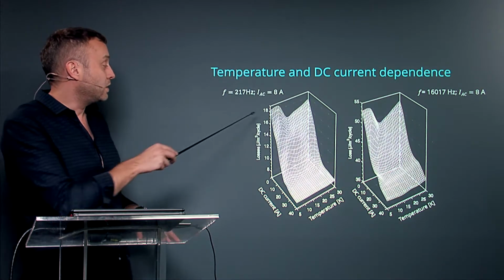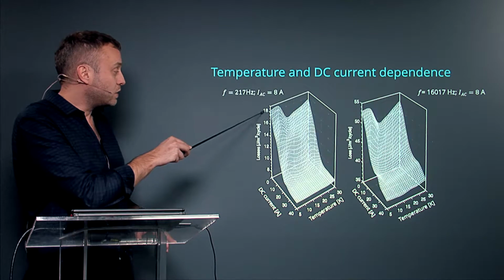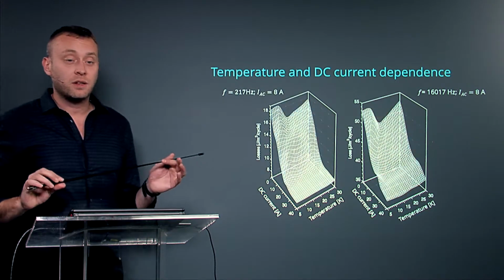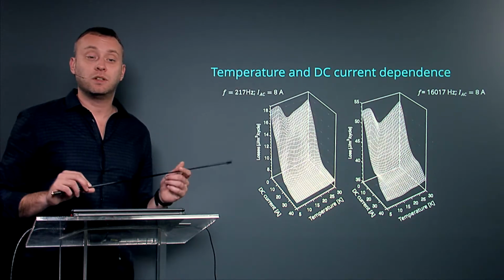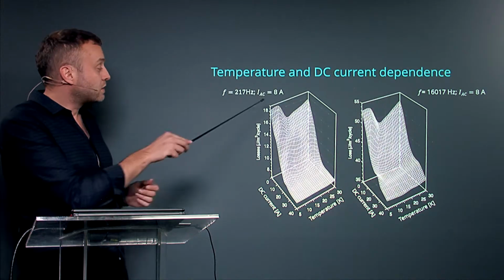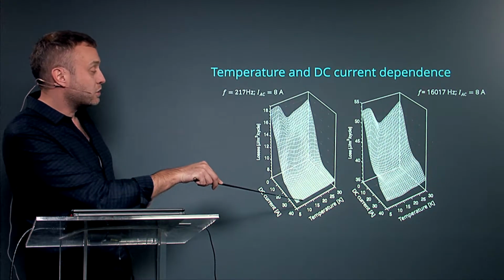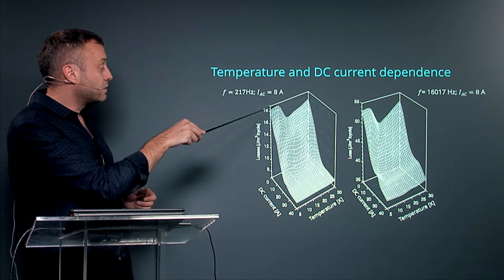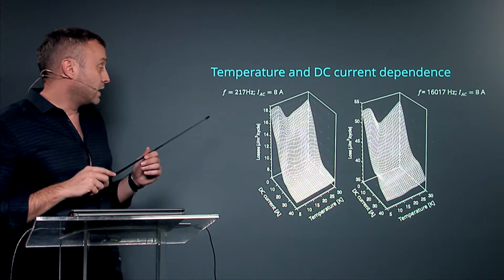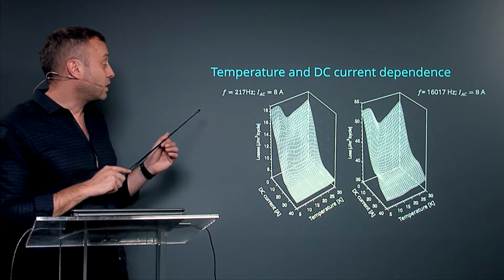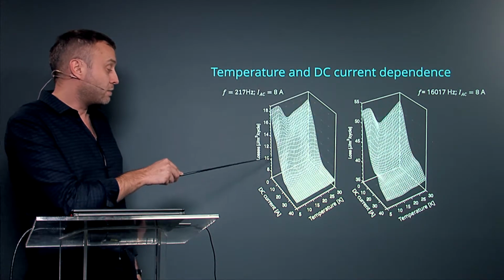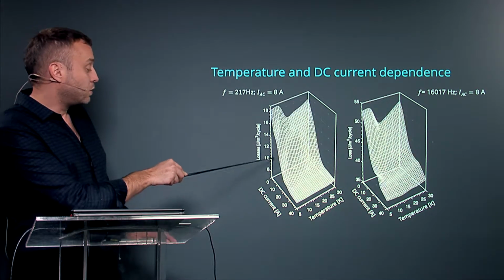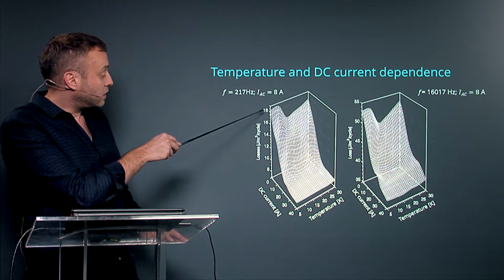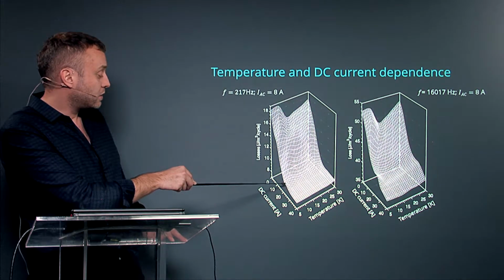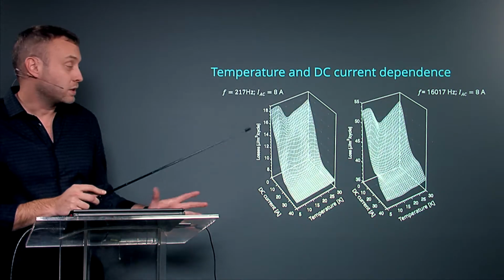So what we see here, for every DC current, is that the temperature dependency is not monotonically increasing as was expected. We see this huge bump at the lower temperatures in both cases, and after this point, the energy loss increases with the temperature, as we would expect. The additional phenomenon is that the energy loss decreased dramatically, as we saw before, with the DC current. So we see this reduction until this point, and then it reaches some kind of plateau.